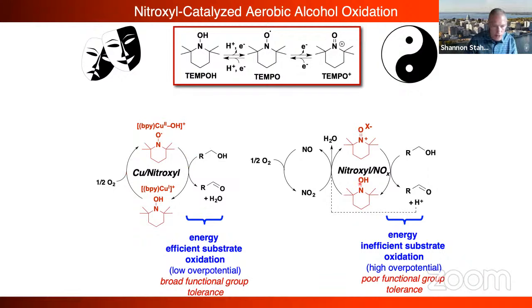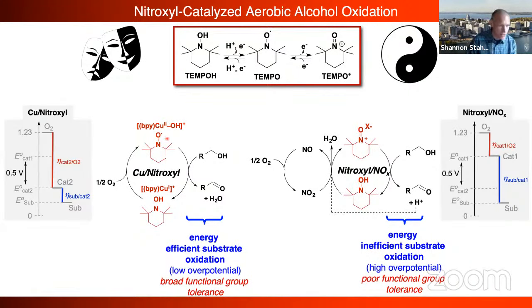In some cases, you may be more interested in the functional compatibility of a low overpotential alcohol oxidation catalyst. What that means is I'm basically moving my oxidant down to the thermodynamic potential of the substrate. That's basically what's shown here. We're wasting all this driving force for O2 reduction so that we get this exquisitely tuned catalyst with a very mild, or hitting with a very soft touch is the way to think about it. Whereas this one is giving it a slug in the gut, basically, and driving this reaction with a strong driving force.